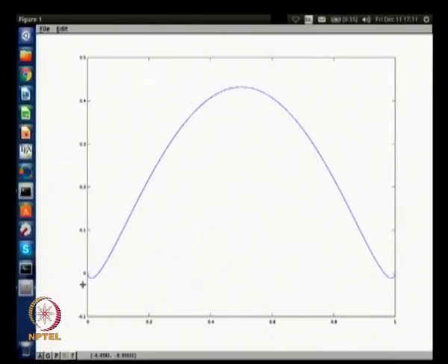But other places, once you are beyond that point, the rate of change of entropy is not going to be very large with composition. So, exponential is not the right way of describing it. The right way to describe is that rate of change of entropy with composition, when you are moving towards the purer components, is very high. As you move away from near pure compositions, the rate of change of entropy is not that high. So, that the contribution from that part of entropy starts coming down.